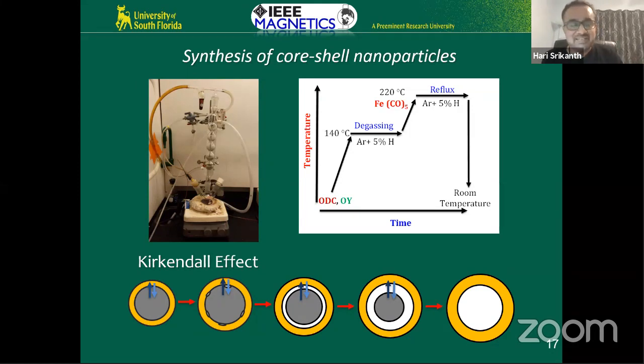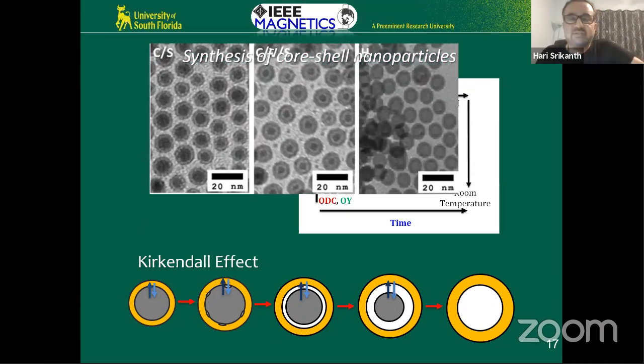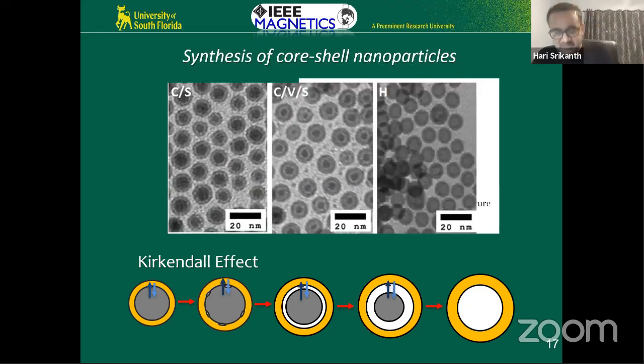This is the Kirkendall effect. So you start by making beautiful core shell particles. You end up after some time as beautiful hollow nanoparticles. So if your goal is to make nice hollow nanoparticles, this is the way to go. Okay. And this was first shown by Paul Alivisatos and his group at Berkeley. And it's well known that if you want to make hollow nanoparticles, you can use this differential diffusion or the Kirkendall effect. So what we did was we did a time analysis.